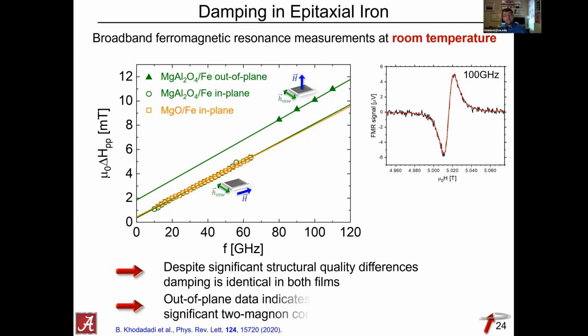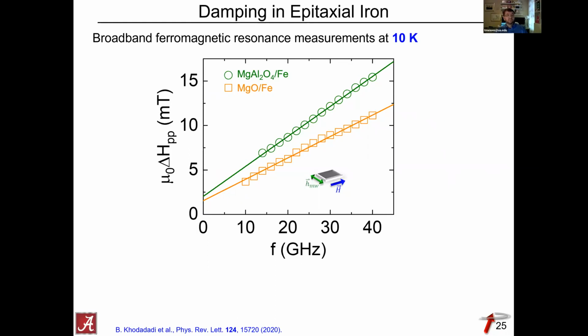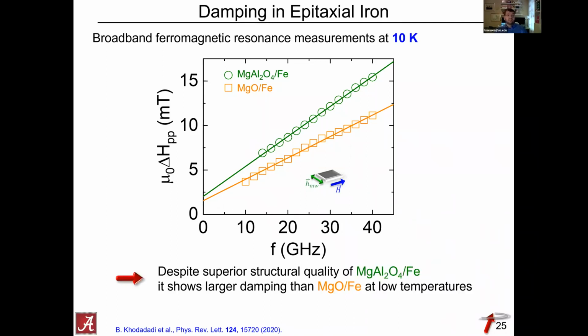So we can also conclude that in our films the two magnon contribution is negligible, which is to be expected because the films were 25 nanometers thick, so any interfacial contribution should drop off fairly rapidly. Now we really have a system where we think we can measure the intrinsic damping of the material. Let's take a look at low temperatures. This is the data as you get them at 10 Kelvin. What you see is that the structurally better film on magnesium aluminum oxide has a larger damping. At first glance this might be a little surprising if it weren't for this conductivity-like intraband contribution, which dominates at low temperatures.